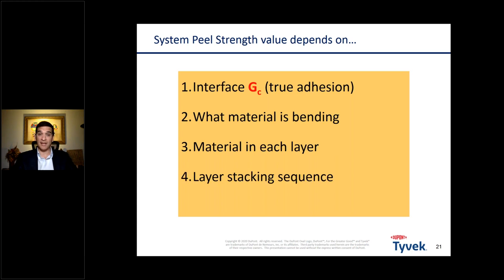The other thing is the layer stacking sequence. If we change the stacking sequence or the thickness of different layers, we're going to get a different seal strength, even if we keep the sealant layer on the other side exactly the same, because of the interaction of other materials, the elastic and inelastic deformation, and the combination of all of that. And finally, the stiffness of the material comes into play.